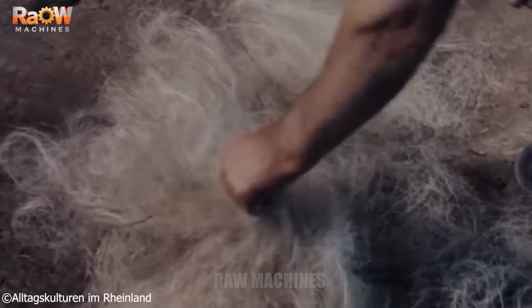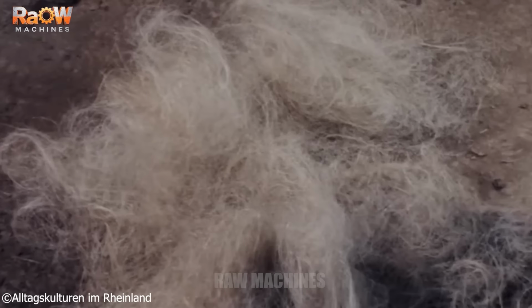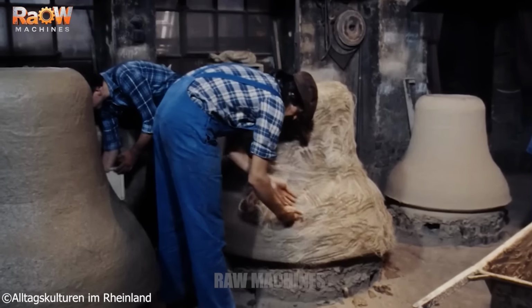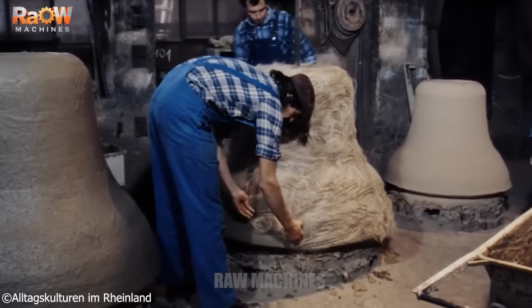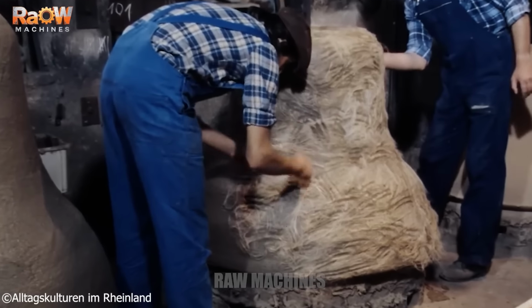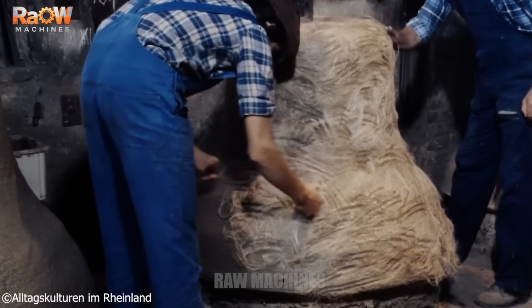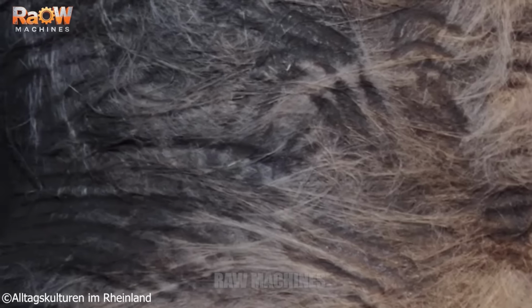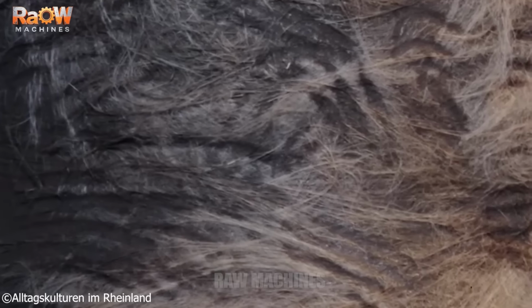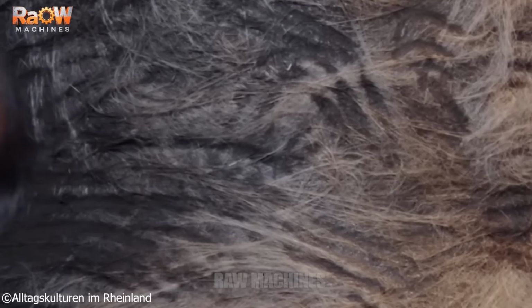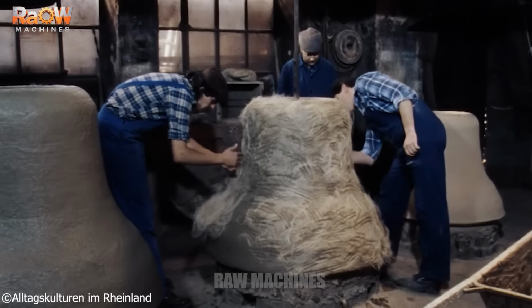The outermost layers are then built up with stiff clay reinforced with jute fibers, ensuring the mold shell is strong enough for transport and for pouring molten metal. Although these layers no longer influence the bell's acoustics, the schablone is still used to finish the surface, in accordance with traditional practice at the Mabillon Foundry.